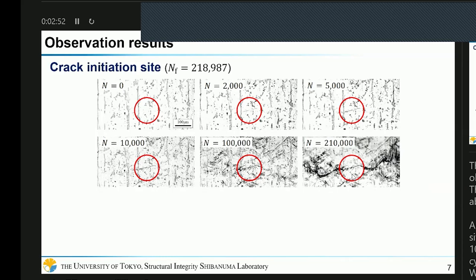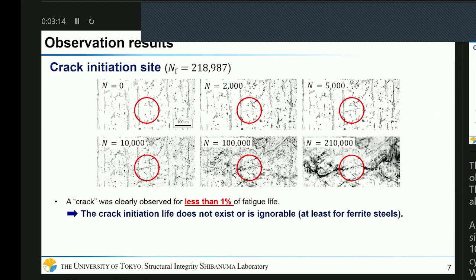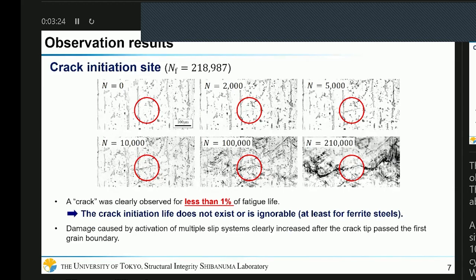So of course, at 0 cycle, we can see nothing. However, at only 2,000 cycles, a crack was clearly observed, even though it was less than 1% of the fatigue life. So it indicates that a crack initiation life does not exist or is negligible, at least for this kind of steel. In addition, from the last photo, we can see that the damage caused by the activation of multiple slip systems clearly increased after the crack passed the first grain boundary. So the boundary between stage 1 and stage 2 may be defined by the first grain boundary like this.